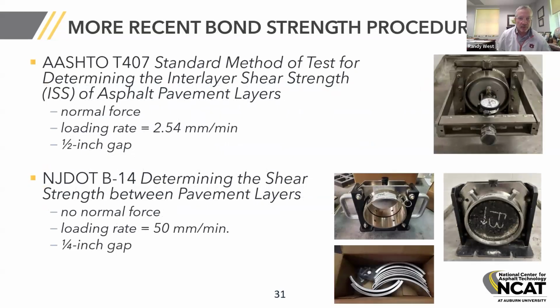Now, more recently, there have been some other studies that developed other bond strength procedures. There's an AASHTO standard developed by Louisiana. It is similar to the method that we used in the phase 1 work at NCAT, and it requires a normal load. But the loading rate that they have in this standard is much, much slower than what we have in the LDOT or the NCAT procedure. And then there's also more recently some work with the New Jersey DOT. They have a bond strength test, and it's much like the Alabama method and the method that Sean is going to talk about in just a minute.